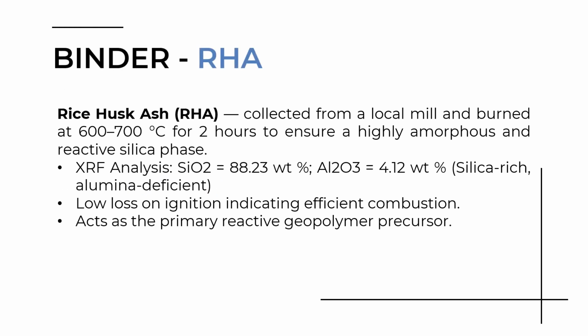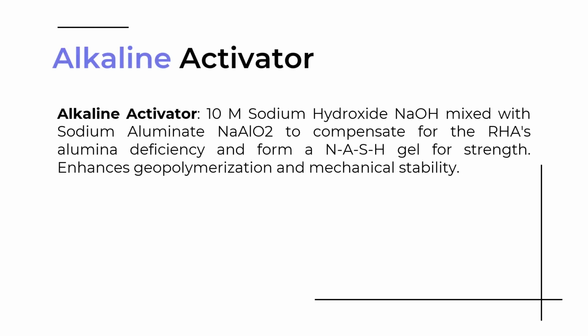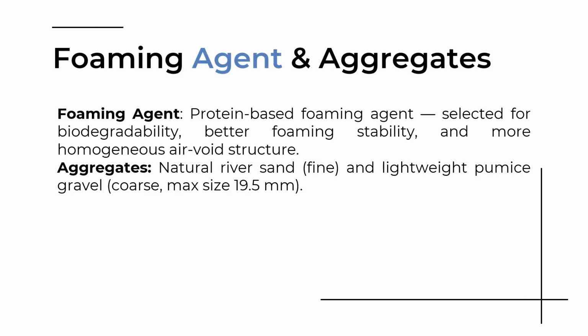For that, we use locally produced materials. Rice husk ash was used as the primary geopolymer binder. From the XRF measurement, we detect that the silica is more than 88%, with alumina only about 4%. For the alkaline activator, we mix 10 molar sodium hydroxide with sodium aluminate to compensate for the RHA aluminum deficiency and to form N-A-S-H gel for strength enhancement. For the foaming agent, a protein-based foaming agent and lightweight pumice aggregate were utilized.